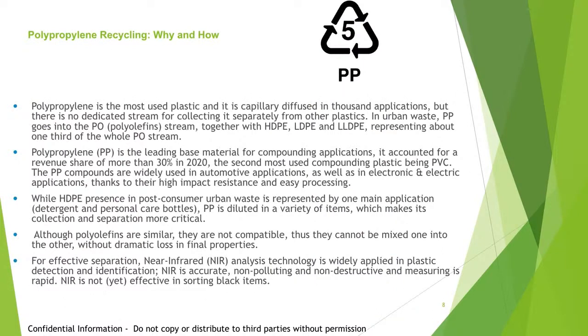Despite the fact that polypropylene is the most diffused plastic in the world, there is no dedicated collection stream, and polypropylene is collected together with all other polyolefins: high-density polyethylene, low-density polyethylene, and linear low-density polyethylene. This creates a problem because polypropylene is not compatible with all other polyolefins. There is the need to separate polypropylene from all other plastics in order to get the best performances out of the recycled material.